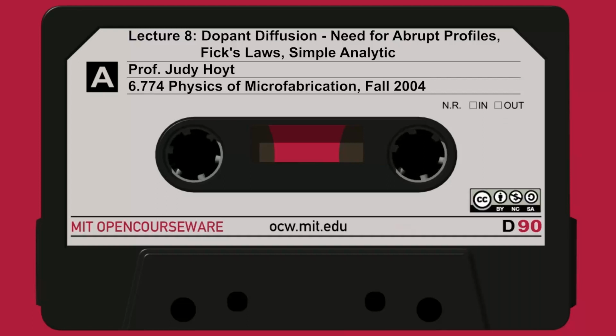Let's go on to slide number 26, and we find that the solution that satisfies Fick's second law is written down by this equation, and in fact it's a Gaussian distribution. The concentration as a function of x and time can be given by that constant dose Q divided by 2 times the square root of pi Dt times the exponential of minus x squared over 4Dt. So that's what's known as a Gaussian profile.